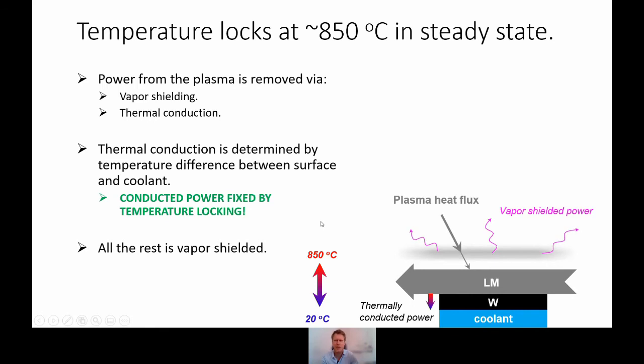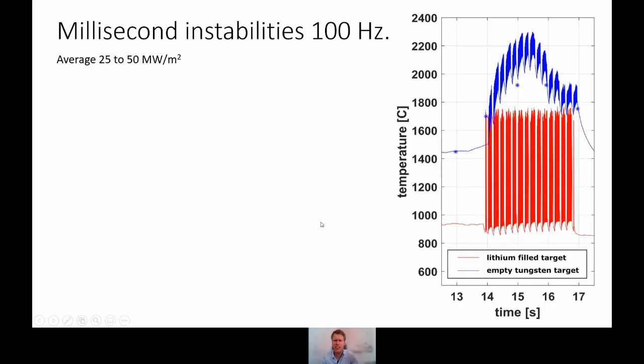So let's take a look at some pulses. We know this works in steady state, but what happens during a pulse? And as I said, Magnum can do this quite well. And what we have done here is the most severe loading that we ever did on a sample like this, which is instabilities of 1 millisecond each applied at 100 hertz. And if you see here, I noted in green that each of these little peaks is actually about 15 pulses that are so close together that you cannot discern them in this figure.